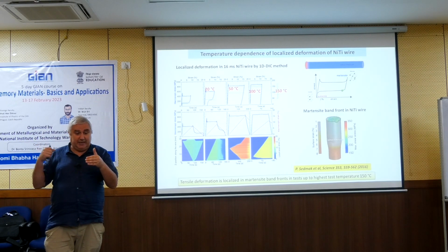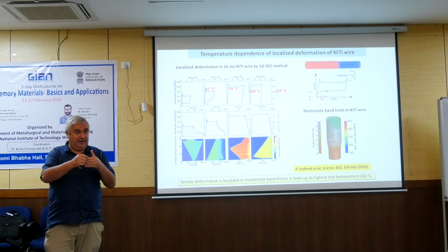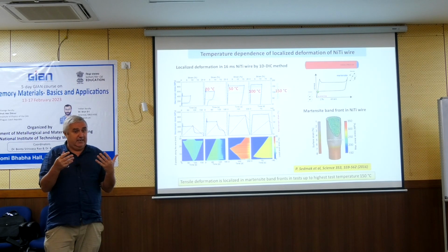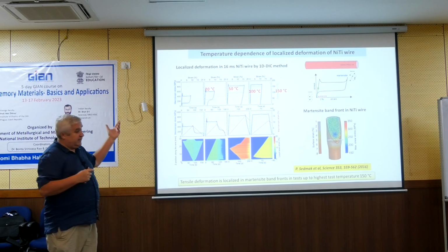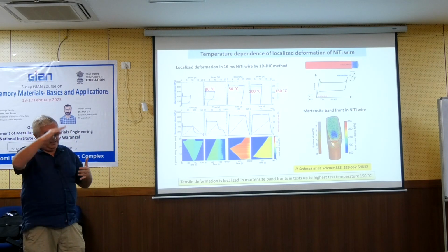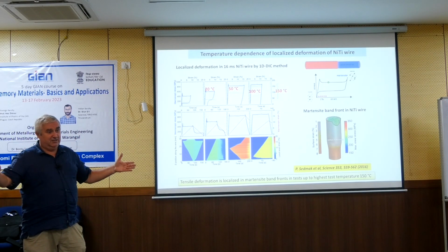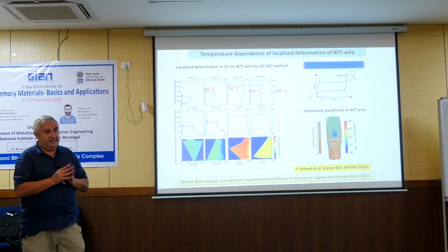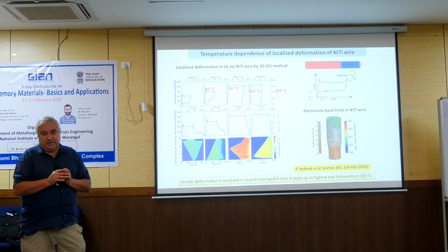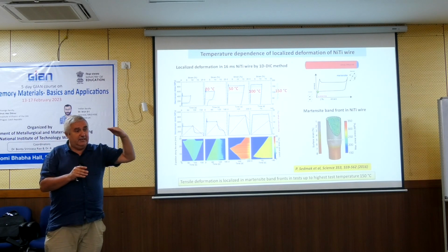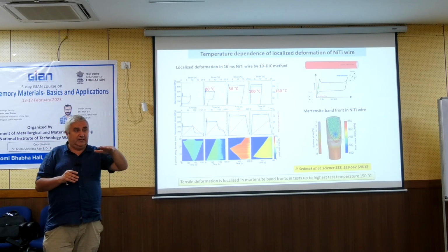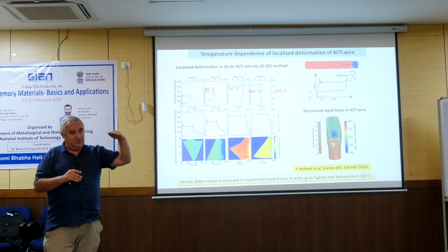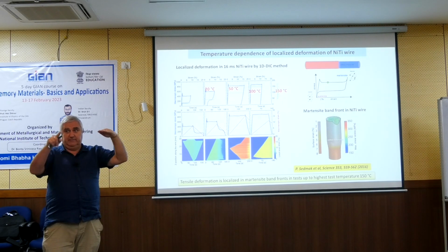If I put some stream of very cold air, it will be almost isothermal, and then the stress strain curve would be very similar in the range of very different strain rates. So in the first approximation, it is strain rate insensitive. And if you imagine, as people who develop actuators frequently do, they put constant force and cool and heat the wire.